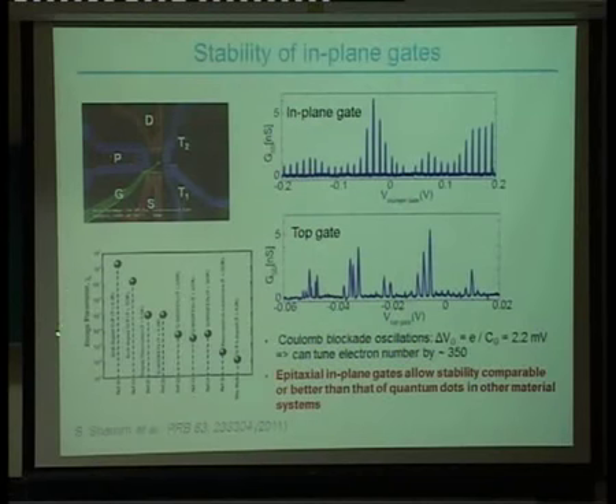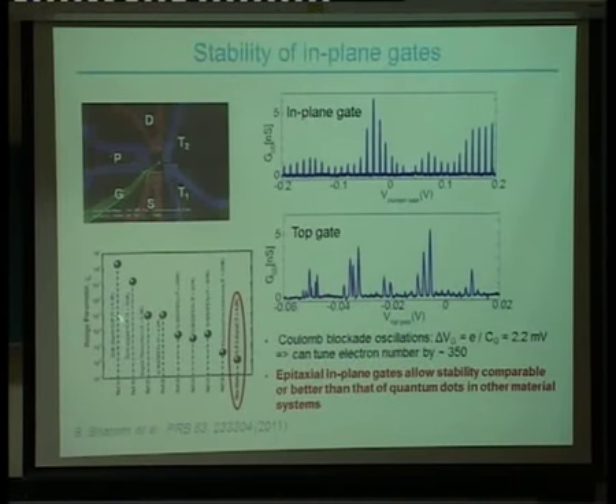And you can actually characterize the noise in these systems by something called the Hooge parameter. It's a phenomenological parameter. And I don't know if you can see, but these are all the different silicon devices that existed in the literature. And for the highly phosphorus-doped silicon down here, you can see that the noise is much, much lower. In fact, it's 6 orders of magnitude lower than for bulk phosphorus-doped silicon at the same density.